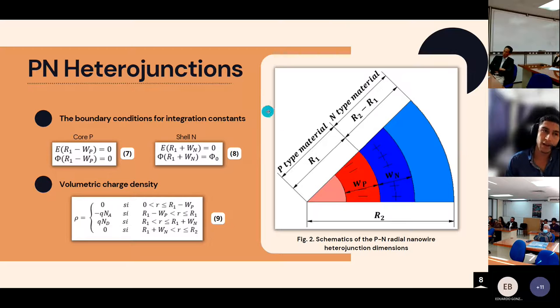For our device, the PN heterojunction, we get the boundary conditions for the integration constants C1 and C2 when we analyze the innermost zone in the nanowire, where the electric field and the electric potential are equal to zero, and the outermost zone of the semiconductor, where the electric field is equal to zero, but the potential is equal to the built-in potential.